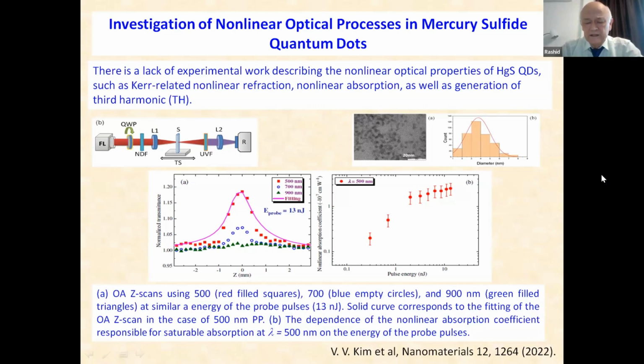Meanwhile, we analyzed the spectral dependence of third harmonic generation. In that case, the scheme is as simple as in the case of Z-scan. Femtosecond laser propagates through the sample, which is placed in the focus, and we analyze the third harmonic signal in that case.